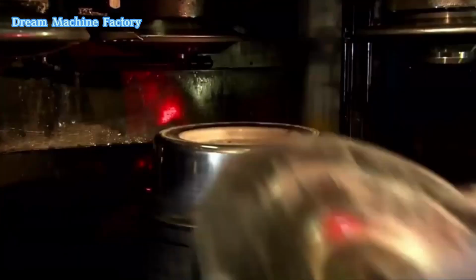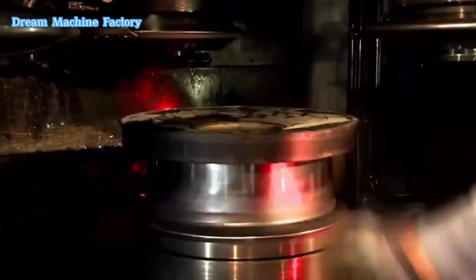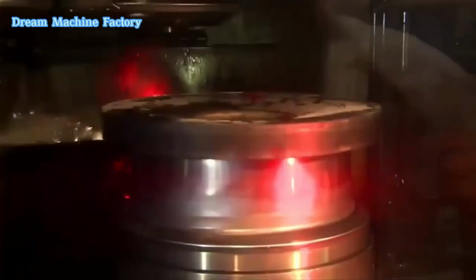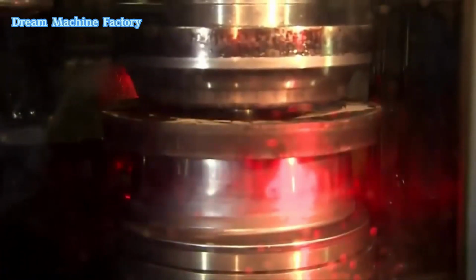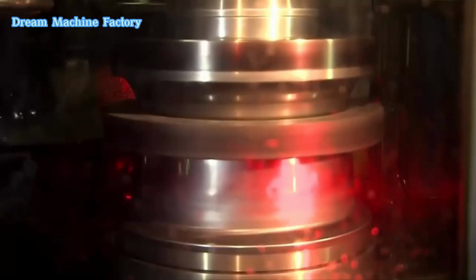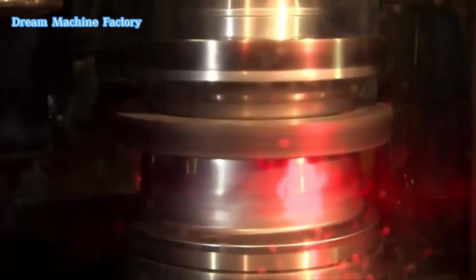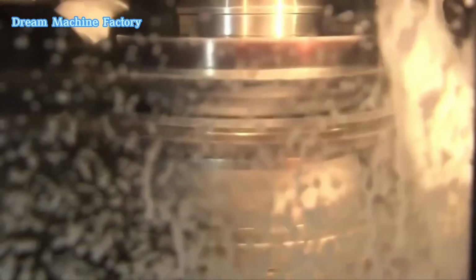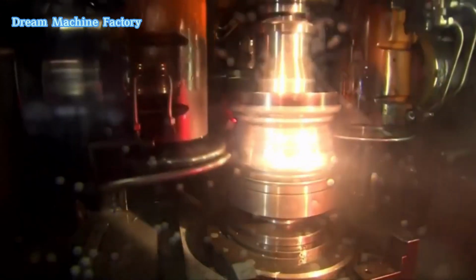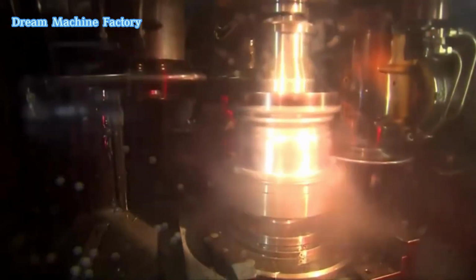After the initial forging, the aluminum disc is placed onto a shaping machine. Here, massive computer-controlled rollers descend onto the disc, applying pressure while spinning it at high speeds. As the aluminum is stretched and thinned, it gradually takes the shape of a wheel rim. Cooling liquids are usually sprayed onto the metal to reduce friction and prevent overheating. In just 45 seconds, the flat disc is transformed into a wheel up to 40 centimeters, 16 inches high.